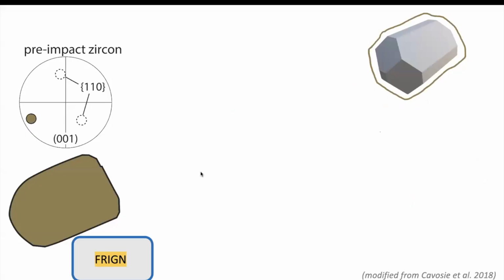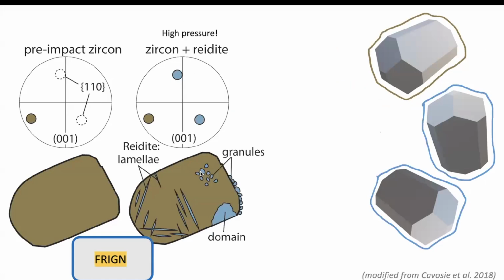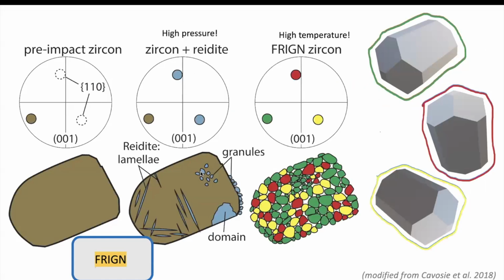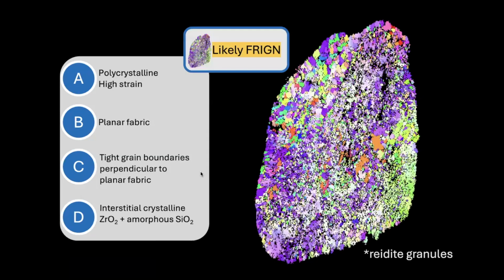So here's the FRIGN mechanism. We start with a pre-impact zircon. We at high pressure make Reidite, and then high pressure dies down, high temperature takes over, Reidite back transforms to zircon. So this grain seems pretty consistent with FRIGN.